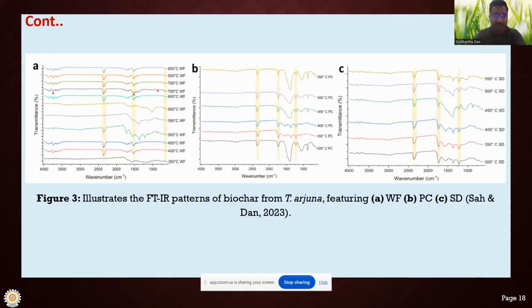And these are the results of our graphite derived from three different sources: the whole fruit of the Arjuna terminalia, second the pericarp, the outermost layer of the Arjuna terminalia, and next only the seed, which we can collect to take graphite. All these three types of sample we checked for different temperature ranges, that is 250 to 900. But in the case of pericarp or seed, we can take only 300 to 500, because as the temperature range is increased, the sample is lost, and at 300 we can see the incombustion of the samples. So the temperature range is only 300 to 500 degrees Celsius, and this is the FTIR spectrum analysis,